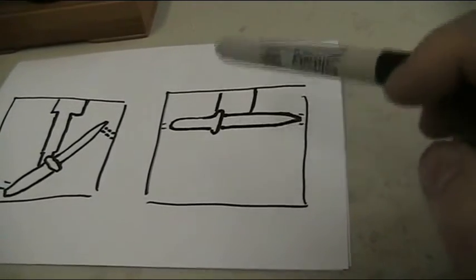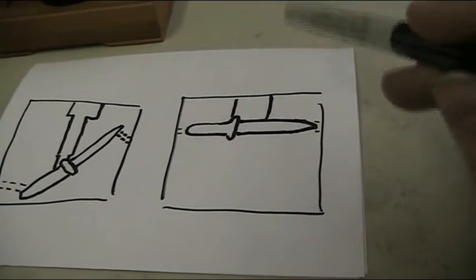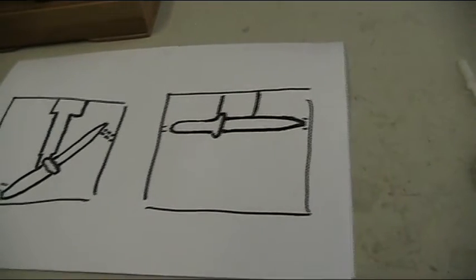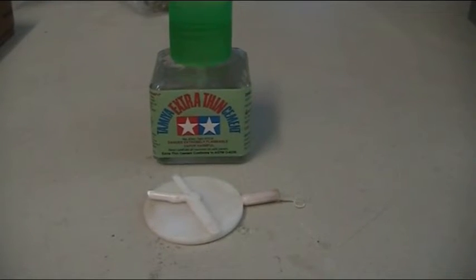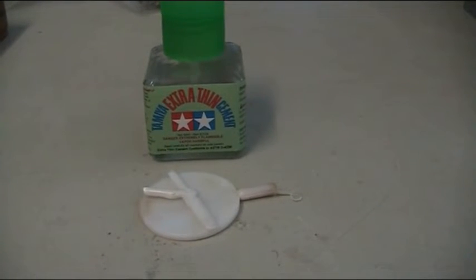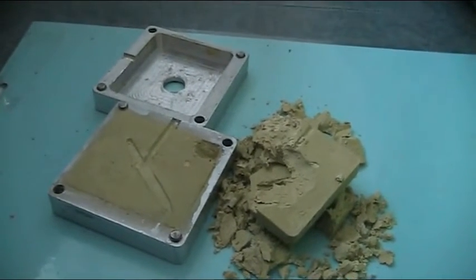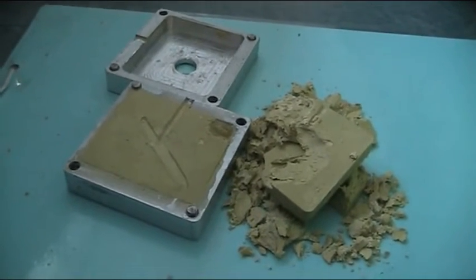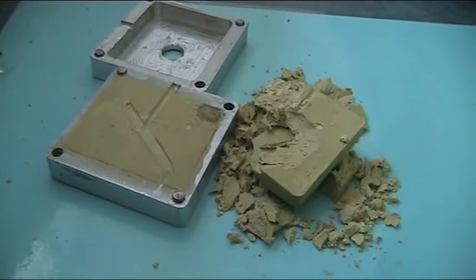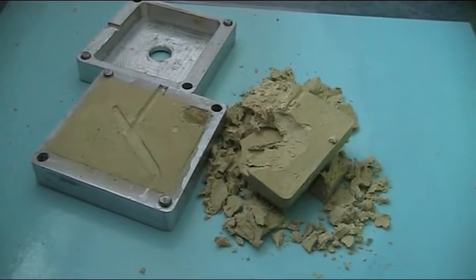And I've also not given up on Milliput. I will try that a second time with a few improvements and some vents to see if I can get a better cast. A quick test - yes, this high impact polystyrene does react to cement and glue together. Also, the spray lube doesn't work out. It gets stuck to the mold and I virtually have to destroy it just to get it out. We're definitely going to use petroleum jelly on the outer frame for an easy pop-out like the resin.